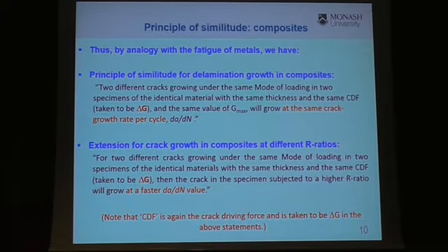Then, by analogy to the metal principle of similitude, we have the principle of similitude for composites. And generally, everything is the same except changing the crack driving force from delta K to delta G, and the K max to the G max.